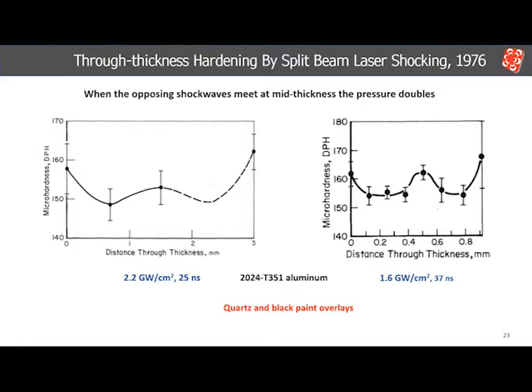In the thinner sheet, it is clear that the average hardness through the thickness was higher than through the thicker sheet, even with the lower power density applied.